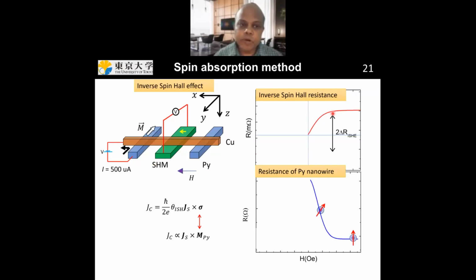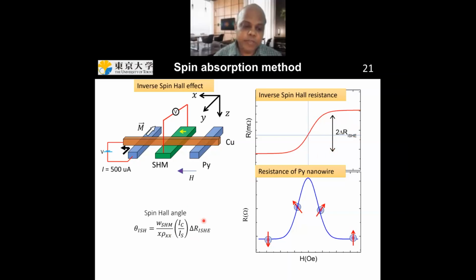And now if you reduce the field to 0, then what will happen is that at 0 magnetic field, this is a ferromagnetic nanowire, so the magnetization would like to align along this y direction over here. So in this configuration, you will detect 0 voltage because this mutual orthogonality condition is not satisfied. So the voltage will reduce to 0. And the same thing will happen if you go to the negative side. And now the difference between these two resistances is called the inverse spin Hall signal. If you know this inverse spin Hall signal, you can calculate the spin Hall angle using this expression over here. And the bottom panel over here shows the AMR measurement of this ferromagnetic permalloy, which we use just to cross-check that our switching fields correspond to our inverse spin Hall resistance values.